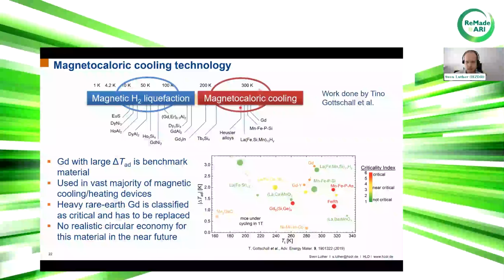So what I present here is mainly the element gadolinium, because this one has an extremely large adiabatic temperature change, and it is regarded as a benchmark material for magnetocaloric cooling technology, because it is used in the vast majority of magnetic cooling and heating devices. In the pulse fields, we have the advantage that we are measuring under adiabatic conditions, which makes our pulse field facility a really good environment to measure the adiabatic temperature change from the magnetocaloric effect.